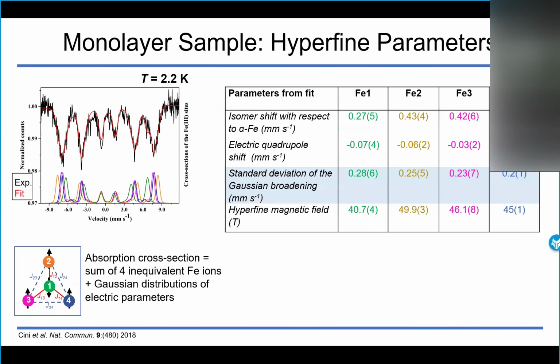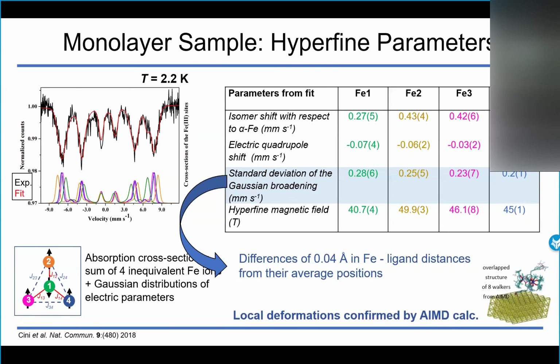Concerning the monolayer sample, we used the same fitting procedure, except that in order to consider that the lines were broader, we had to consider a Gaussian distribution of the electric parameters. And this translated into the fact that we have differences of the order of 0.04 angstrom in the iron-ligand distances from their average positions. These local deformations were undetected by other X-ray characterization techniques, but were confirmed by AIMD calculations. So, in conclusion, we demonstrated that with the synchrotron Mössbauer source, we could have information on the hyperfine parameters of very thin samples.